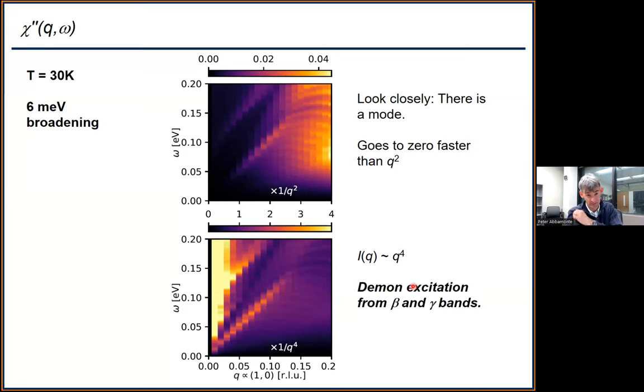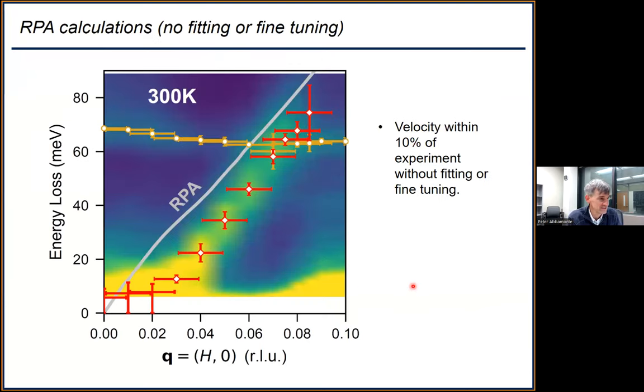So here's an interesting thing. Strontium ruthenate is theoretically expected to have a demon, and we did an experiment and we saw a gapless collective mode. So wouldn't it be interesting to compare them, put the theoretical curve on the experimental curve and see if they match? And that is this. This is momentum on this scale, energy on this scale. The color points are the experiment. The gray line is the RPA. And the velocities are within 10%.